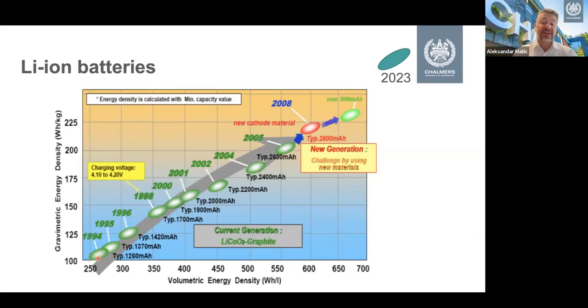And you can see that with the same base technology, we have actually increased the performance of the cell almost three times, going from less than 100 watt hours per kilo, which is the way that we measure the energy density of lithium ion cells. Today, actually, the best cell... So you see this graph stopped in 2008 and are now projected where we are today. We are somewhere here off the chart, with cells approaching something like 300 watt hours per kilo.